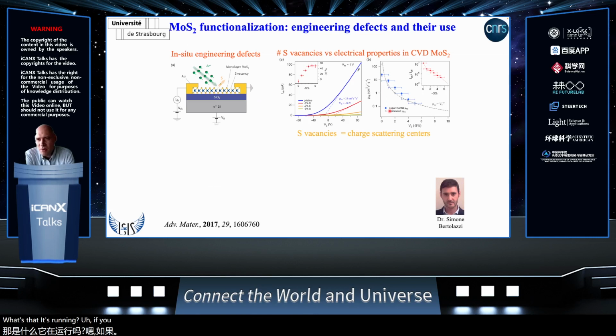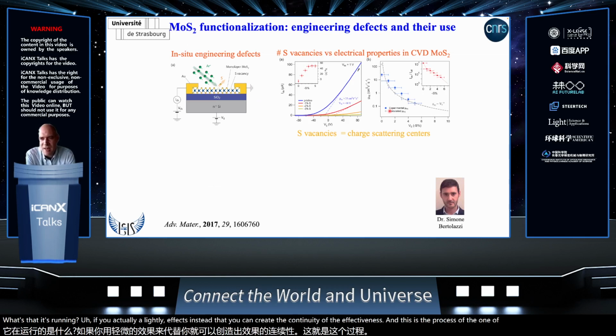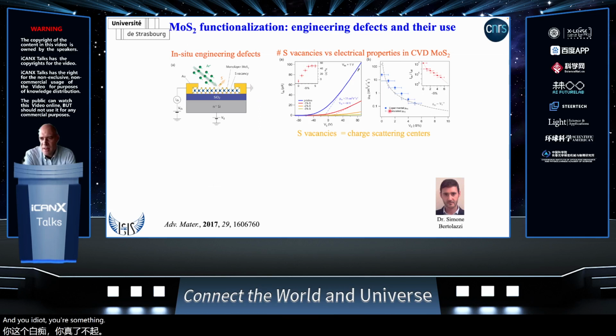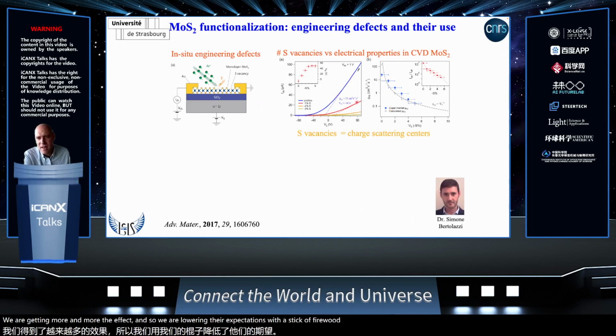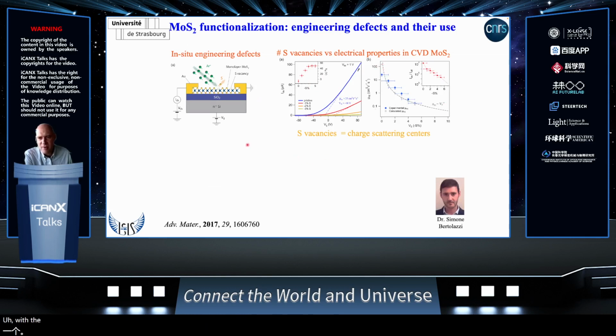If you actually like defects instead, you can generate defects easily. And the easiest approach is to take the argon beam of an XPS and irradiate your sample. And so you can see here that upon irradiation, we are creating more and more defects. And so we are lowering the electrical characteristics of our single flake. You can see how the mobility decreased drastically upon irradiation.